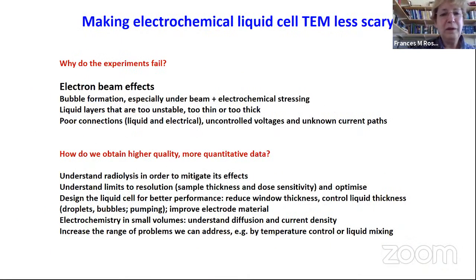So with our practical outlook on liquid cell microscopy, I think a good way to ask how valuable this technique is, is to think about why do the experiments actually fail? You're a student sitting down trying to do this stuff. What is it that goes wrong that means that you don't get good data? My experience is that the most important difficulty, let's say, is electron beam effects. And this could include the formation of bubbles, especially when you have electrochemical stressing, as well as the effect of the beam on the water.